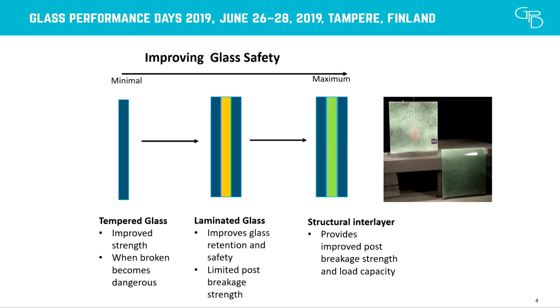If you then take that one step further and you laminate it, you've now already greatly improved the safety, because when the glass breaks, the glass shards adhere to the interlayer and prevent injury from the glass shards. However, the post-breakage strength is not necessarily improved. In some cases it is, depending on the glass type used, but there's still a vulnerability and a weakness in the post-breakage glass strength. If you want to improve that even further, you go to a structural interlayer. Not only do you have the post-breakage glass retention properties, but now you have post-breakage glass strength. So that's the evolution of improving glass safety, going from basic glass to structural.